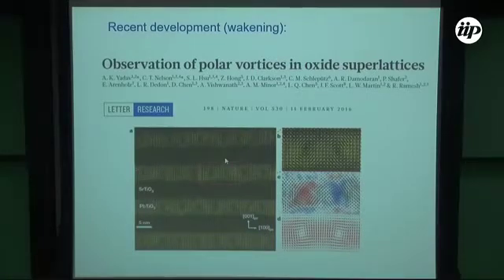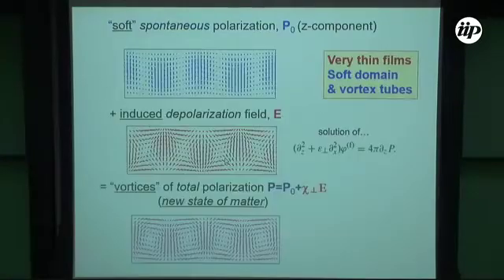Very fine. Actually, it's also a question about terminology, but this vortex is not a vortex alone. It is really a periodic structure of vortices and antivortices. For me, this is the same as the soft domains that I just described, because following the Landau-Lifshitz approach, we consider the polarization as an order parameter, but in addition to this order parameter, we also have some kind of induced polarization, because the distribution of polarization creates depolarization charge. Depolarization charge creates an internal distribution of the field that, close to TC, penetrates somehow. And this field created by polarization will also create an induced component of polarization. If we add to the real order parameter the induced part of polarization, we obtain the vortices.